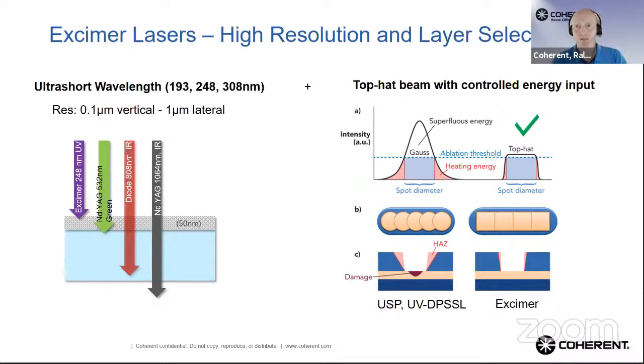Excimer lasers provide highest resolution and layer selectivity in surface processing. And that is, of course, mainly due to the ultra short wavelength. So many people these days talk about ultra short pulses, femtosecond, picosecond, but here we are really at the ultra short wavelength edge. And that means Excimer lasers provide 193, 248, 308 nanometer, depending on the gas which is used. And by that, we have a really shallow penetration depth into any material, polymers or other types of ceramics, for example. So typically the depth per pulse is just below 100 nanometers. So that is really vertical resolution. And if we want, we can also add lateral resolution.